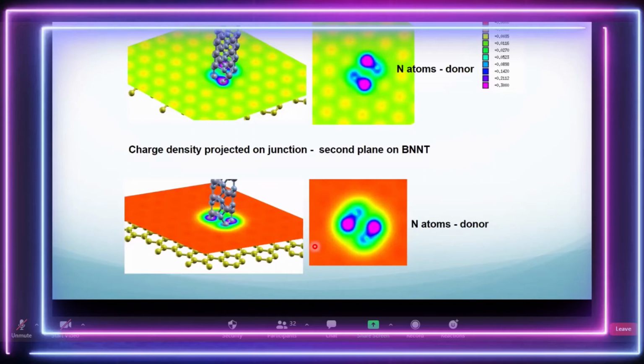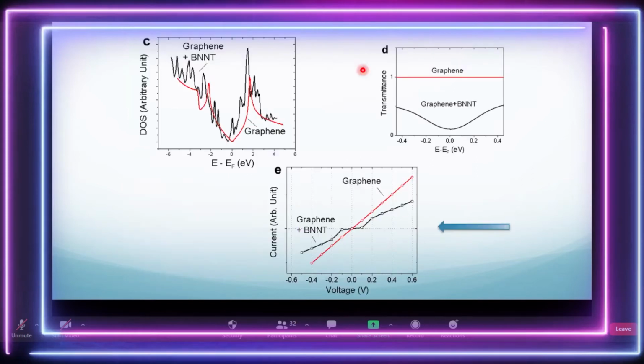And you go further and look carefully: is graphene accepting electrons from boron nitride, or vice versa? You can see nicely that the N atoms, where we project out the different planes on the BNNT, are indeed acting as electron donors. This is the excess electronic density, if you look at the scale here. As you move out, the density is more or less small. So indeed, we have a localized charge density in the vicinity of the nitrogen atoms sitting on graphene. From there, you calculate the density of states, the transmission function, and the IV characteristics.